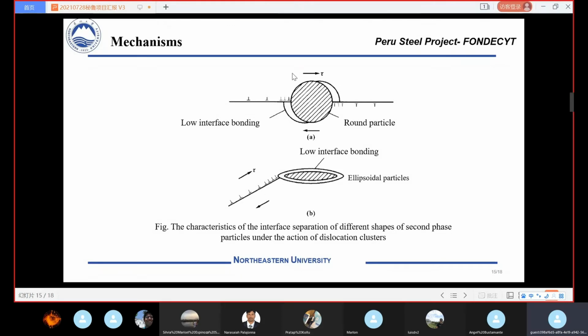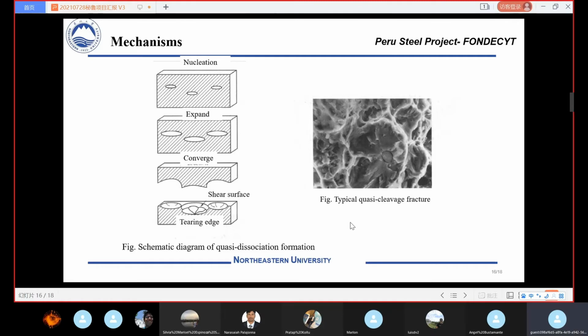The upper one is a round particle, and the second one is an ellipsoidal particle. Here we can find what we call debonding, at the interface between the matrix and the particles. So the round particle is equivalent to a micro void, and the ellipsoidal particle is equivalent to a micro crack for the crack initiation process. And the potential quasi-cleavage crack initiation is micro void, cluster, and hard particles.